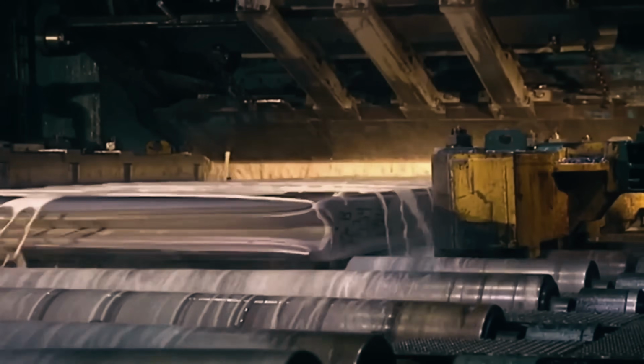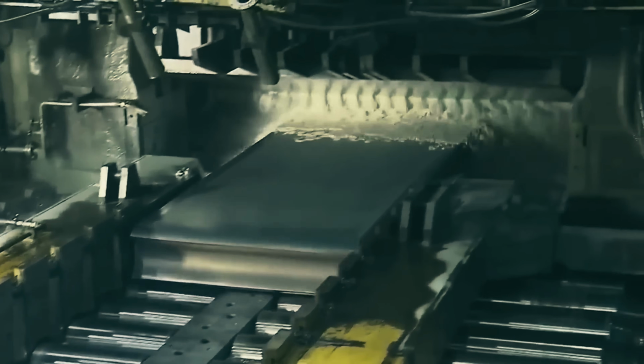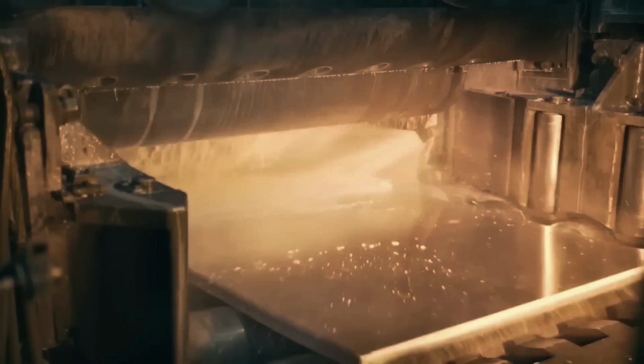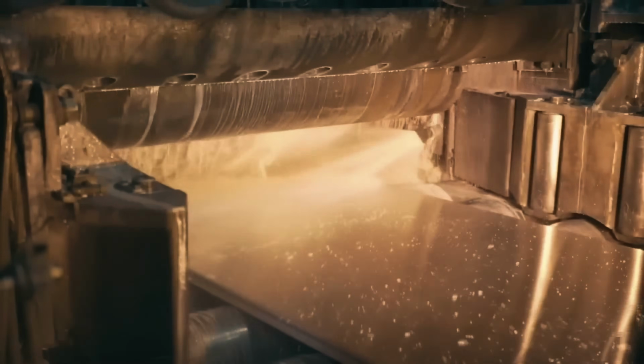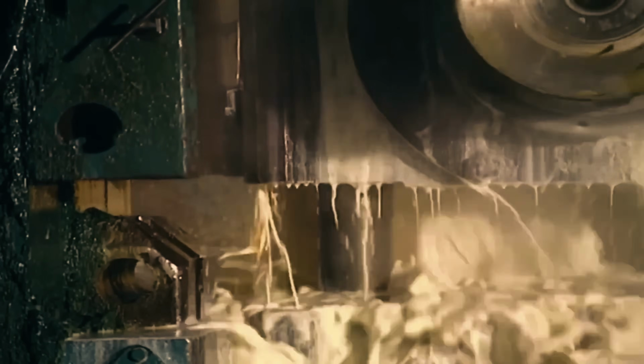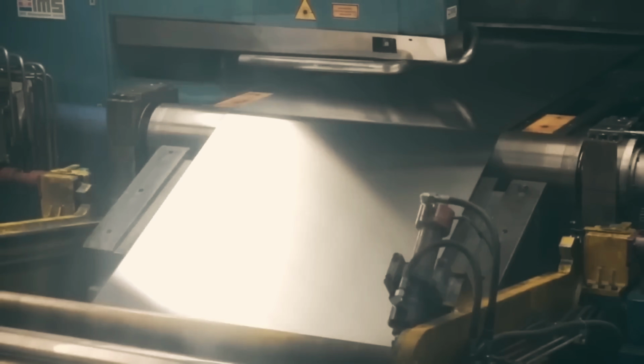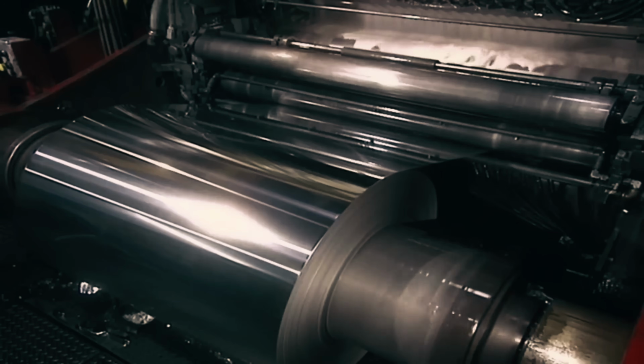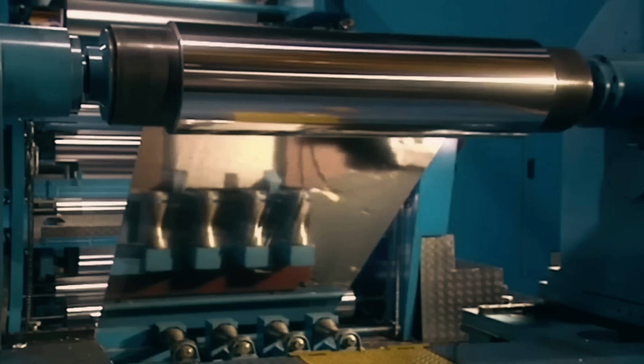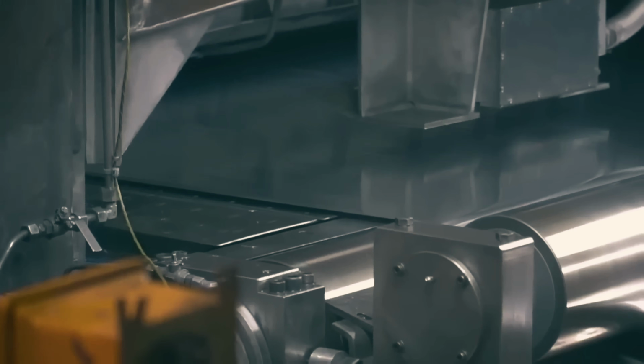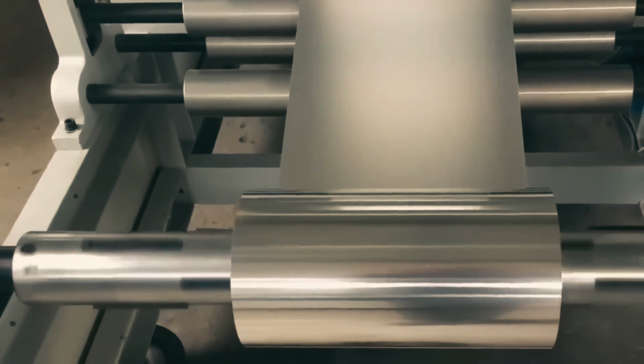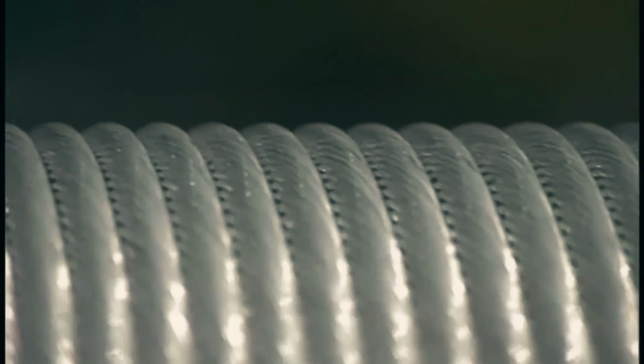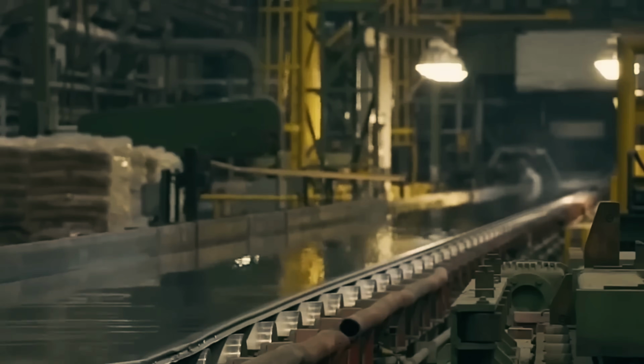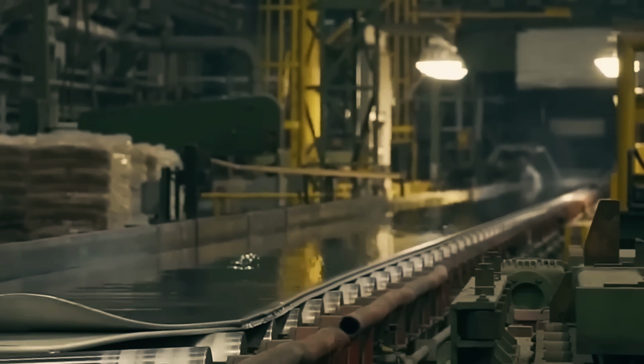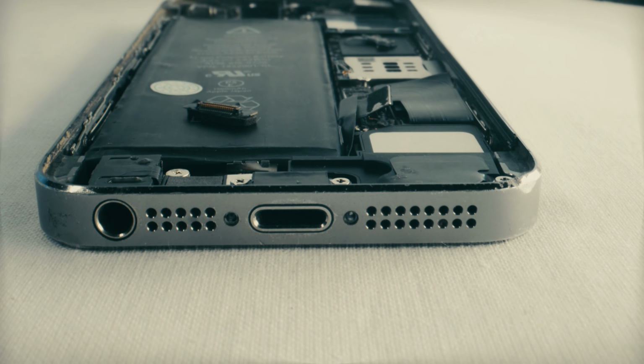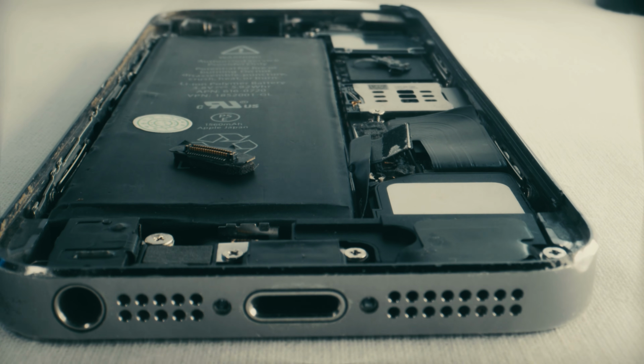Raw aluminum straight off a rolling mill or extrusion press is soft, dull, and completely unprotected. Many products go through a finishing process called anodizing, where the metal is submerged in an acid electrolyte bath and once again hit with an electric current. This time, instead of pulling atoms apart, the current builds up a thin, extremely hard layer of aluminum oxide directly on the surface, essentially growing the metal's own natural rust into a protective armor on purpose, under controlled conditions, rather than letting it happen randomly outdoors. That anodized layer is also porous enough to absorb dye, which is how aluminum water bottles and phone cases end up in bright, saturated colors that never chip off like paint would.